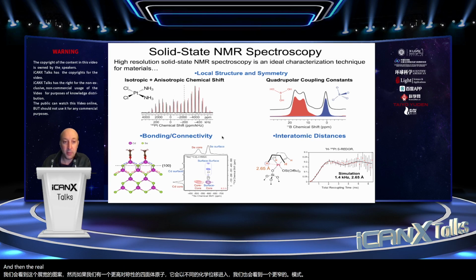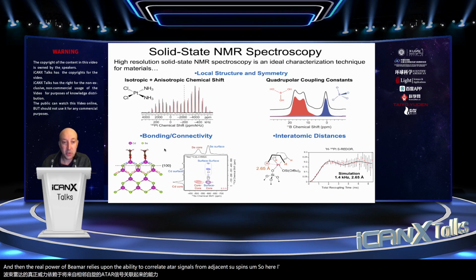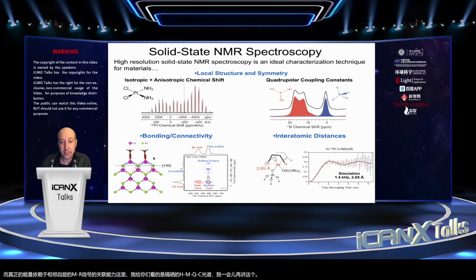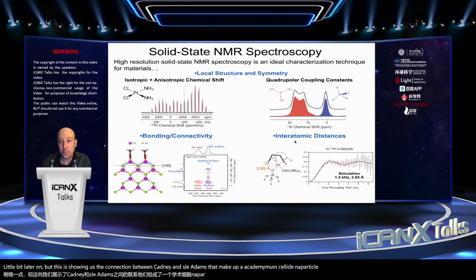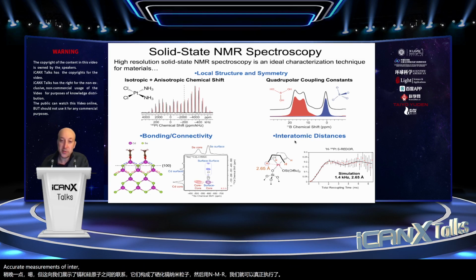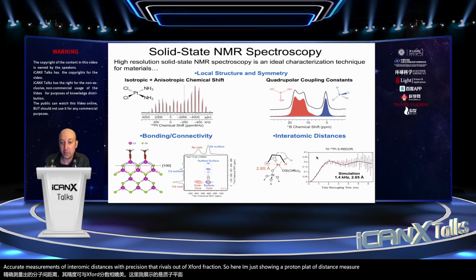And then the real power of NMR relies upon the ability to correlate NMR signals from adjacent spins. So here I'm showing you a cadmium-selenium HMQC spectrum. I'll talk about this one a little bit later on, but this is showing us the connection between cadmium and selenium atoms that make up a cadmium selenide nanoparticle. And then with NMR, we can really perform accurate measurements of interatomic distances with precision that rivals that of X-ray diffraction. So here I'm just showing a proton-platinum distance measurement for a platinum molecule that's supported on the silica surface.